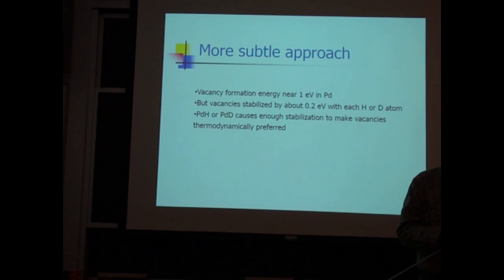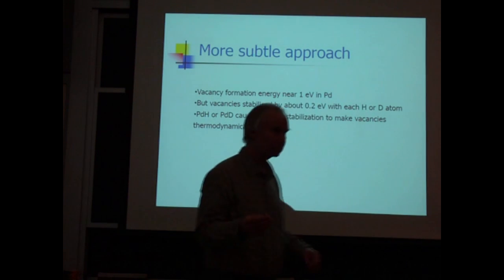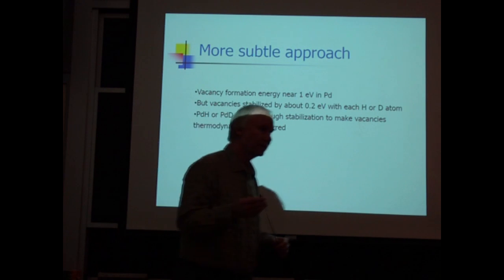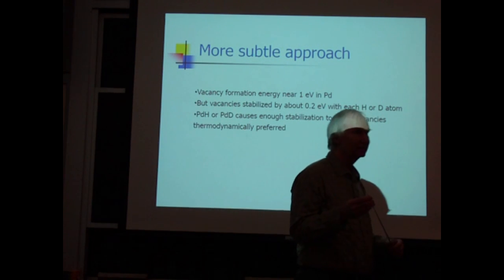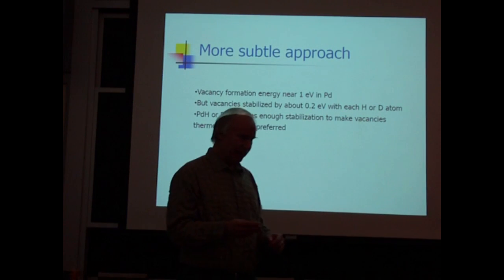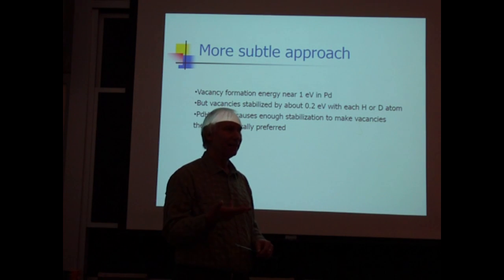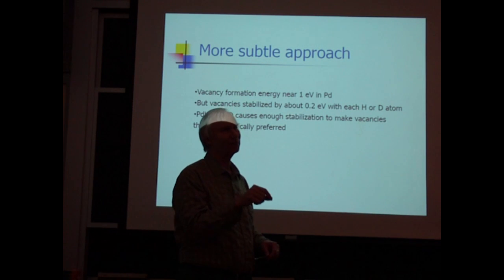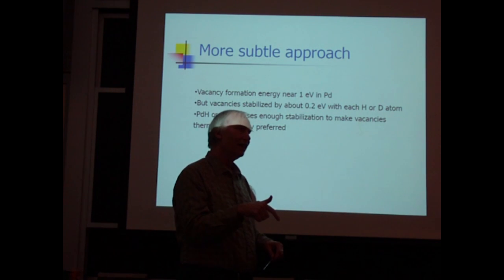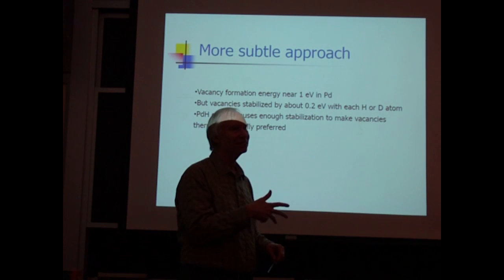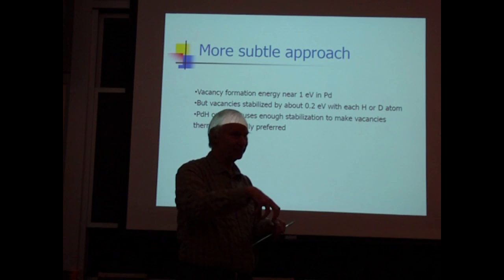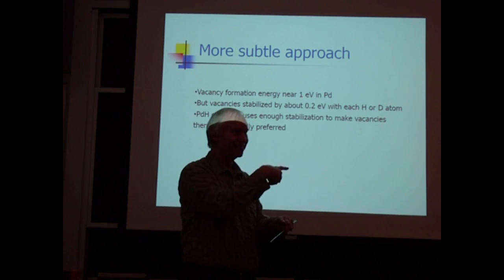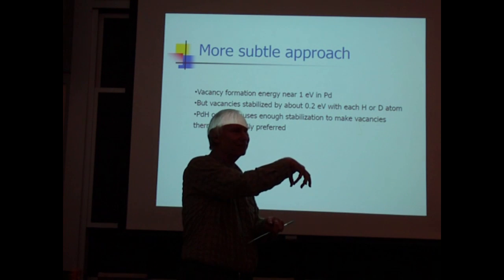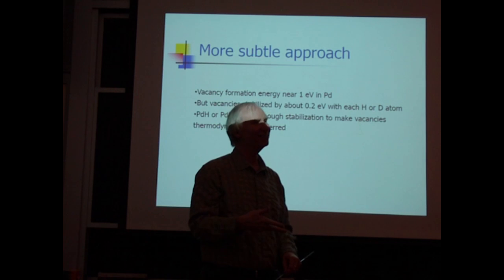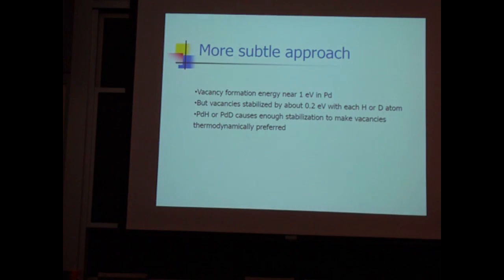Just for understanding, does the stabilization occur because the hydrogen atom takes the place of a palladium atom in the lattice, or does it go in between? As we saw yesterday, the hydrogen and deuterium has a certain electron density it likes. At the site of the vacancy, that's where the palladium's missing, the electron density is very low. The hydrogen wants to see a higher electron density. So if you put a hydrogen at the vacancy point, it's going to look around and say, higher electron density over here. It's going to wander off until it finds its preferred electron density, which happens to be very close to the octahedral site. Good question.